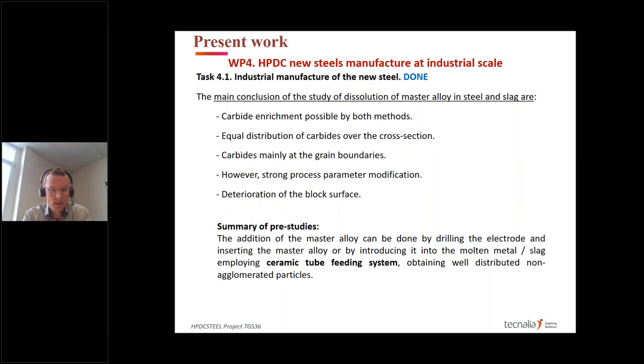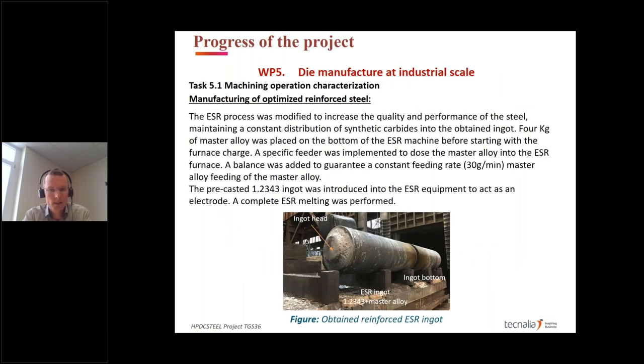A summary given by the pre-studies is as follows: finally we understood that drilling holes into a very large industrial scale electrode is not feasible. So that's why finally we implemented a feeding system in our ESR plant at SWG on industrial scale. What you can see here is our ESR ingot after remelting and feeding the master alloy. So finally, we produced an industrial scale ESR ingot with an average weight of approximately 18 tons. And there, during the processing in the ESR plant, we had the continuous feeding of master alloy.